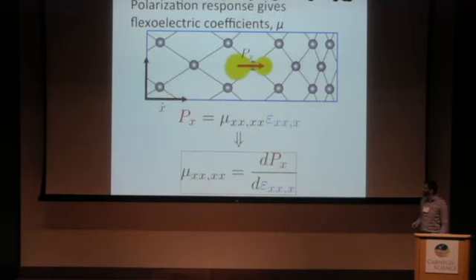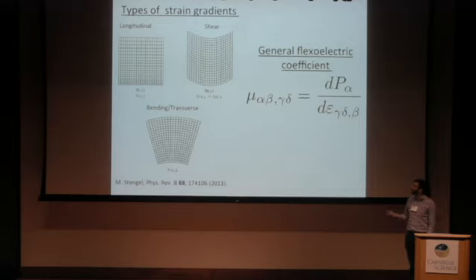The way that we discuss the flexoelectric effect, just like the piezoelectric effect, is through these flexoelectric coefficients that relate the polarization, in this case in the x direction, to linear order to the strain gradient. In our example of a longitudinal-type strain gradient, also in the x direction, all of the four indices of the flexoelectric coefficient are the same. Of course, we could have a variety of different types of strain gradients, including shear, transverse, and also longitudinal. A general flexoelectric coefficient will look kind of like this. So our goal is to calculate all of the flexoelectric coefficients for a given material from first principles density functional theory calculations.